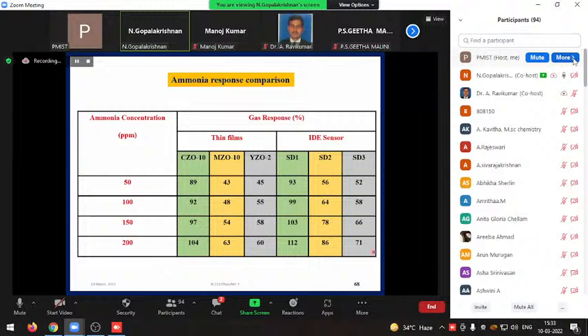Even then, all these films are only made in prototype devices, not made in clean rooms or any other lithography facilities. Even then, in this case, we showed that IDE sensors are better than thin film sensors. That means if at all we want to make sensor devices, it is better to fabricate the device based on IDE rather than thin film sensor. That is because our surface area is very large, because we made an interdigital electrode. See, all this sensor response is higher than that of the corresponding thin film sensor. That is what I want to emphasize.